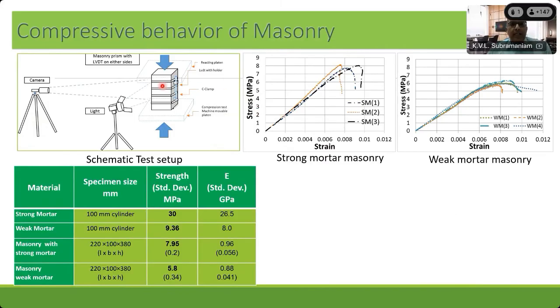So when we actually look at the behavior of masonry and we apply a compressive stress on this, let me go back to this case of the soft brick and the stiff mortar, and the two cases that we considered, the strong mortar case and the weak mortar case. Now, if you remember, the brick had a compressive strength of 15 megapascal. The mortar strength for the strong mortar was 30 megapascal.